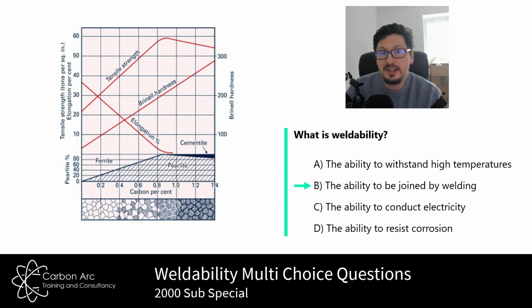Okay, what we see is as carbon increases, tensile strength goes up. At the same time, hardness values go up. Now, this graph shows Brinell hardness. I prefer to work everything with hardness figures, but it's the same sort of pattern. Tensile strength's going up, hardness is going up. Elongation, being a measure of ductility, is coming down as hardness goes up. So the harder something is, the higher tensile strength it has, the less ductility it has.